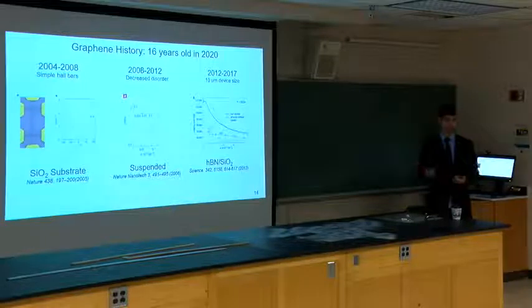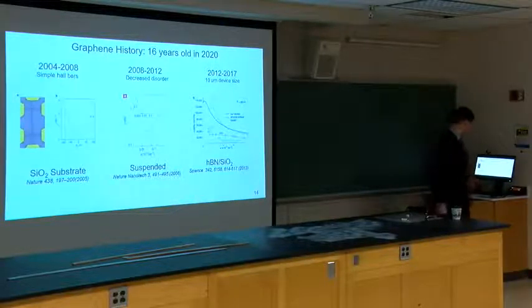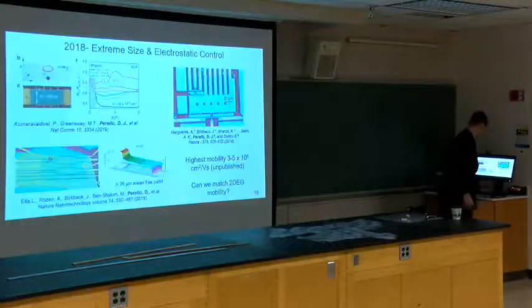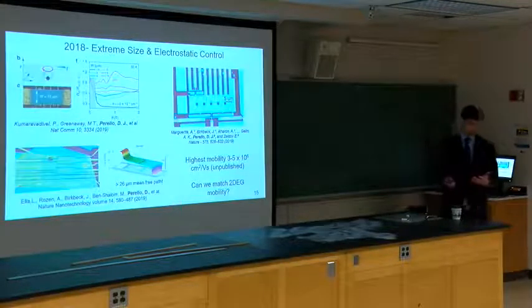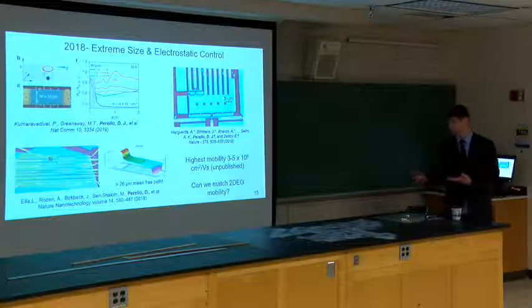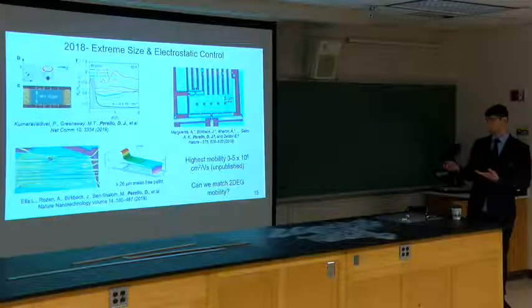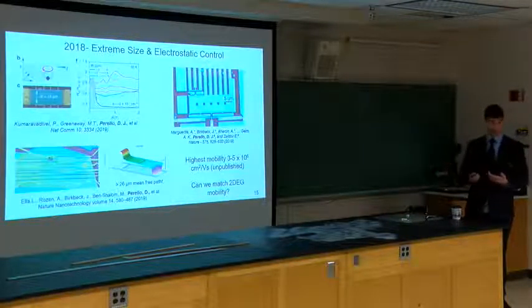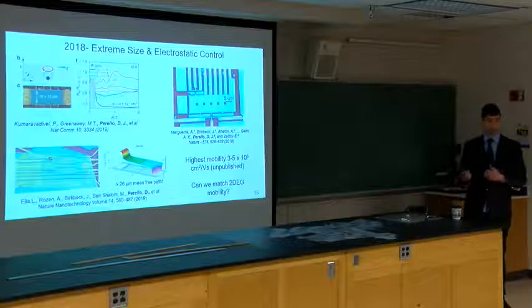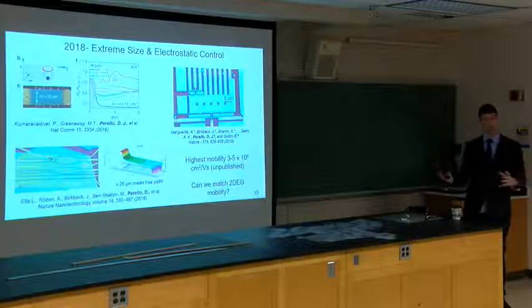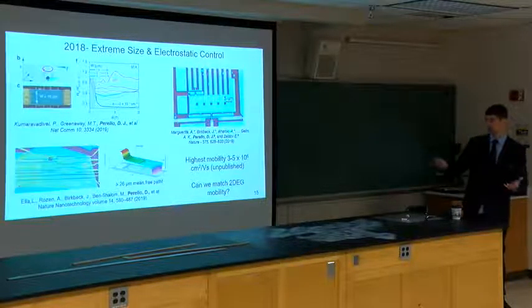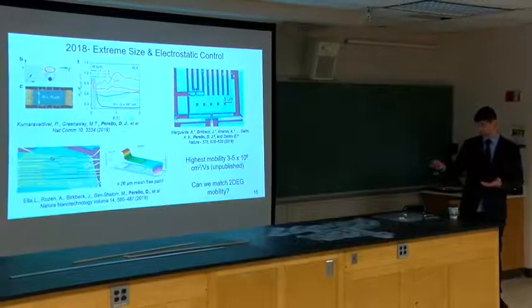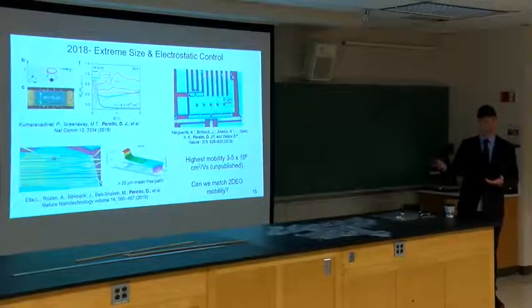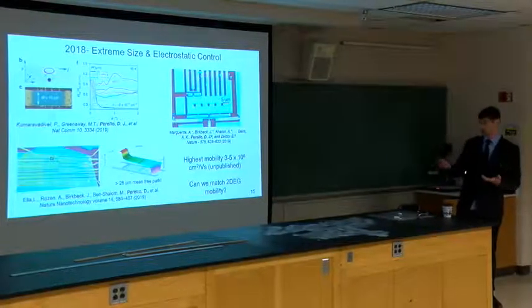we're limited by the phonon mobilities at room temperature, and as we go to low temperature, then we can look at more fun physics. So the recent work, though, and I'm just showing 3 of my recent works, show that there's a lot of physics, especially now that we can make very big devices that are ultra clean. So you can look at magnetophonon resonances that show up in very large devices, which weren't previously possible.